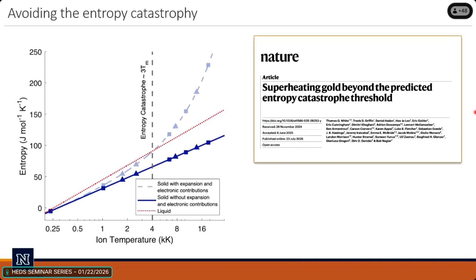And you might say to me, if the ultimate limit of superheating is based on this entropy crossing, did I create a system where the solid has higher entropy than the liquid? And the answer is no. That would be weird to suggest, although there are some things that can happen. What we said was that if you calculate the entropy crossing, so here's the entropy of a liquid, and here in the light blue is the entropy of the solid, and they cross at 3 times the melt temperature for gold. But if you heat something up rapidly such that it cannot expand, then the entropy of the solid becomes this dark blue line, and the lines no longer cross. So that was our explanation for this in the paper.